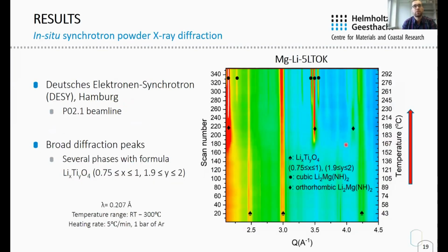In order to understand further the processes taking place upon desorption, the evolution of the crystalline phases was studied by in situ synchrotron powder X-ray diffraction. The sample with potassium was heated from room temperature to 300 degrees, and every 15 seconds diffraction data was collected. The data is plotted in a 2D contour plot, where reddish colors indicate higher intensity.